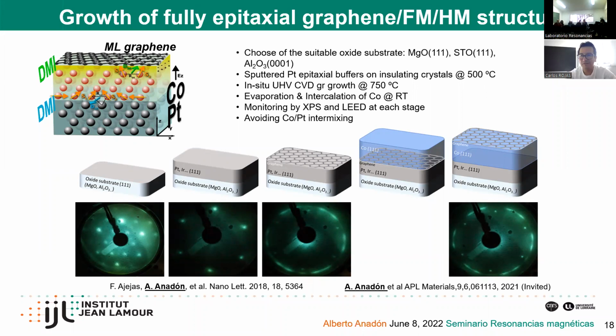So we can do a few nanometers of platinum or iridium grown by sputtering, and then we heat the sample in the same way, and we put gas in the same way. So the growth process is basically the same as what we use for a monocrystal, but you use a thin film. And then this thin film can be patterned, or you can do as you want, for example, to prepare devices to measure anything that you want.